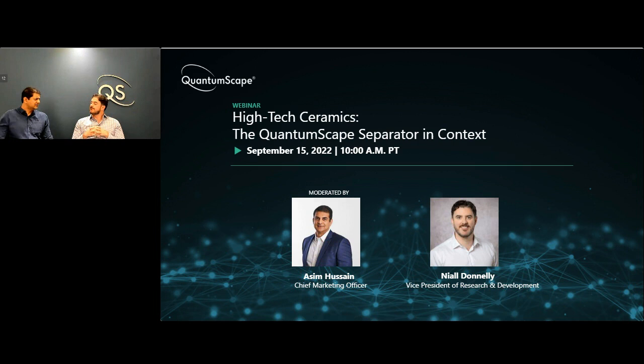Right. And is that because the separator isolates the cathode and the anode so distinctly as a solid state? That's right. In a conventional lithium ion, you have to be very careful about the compatibility of your electrolyte with both the high voltage on the cathode side and the low voltage carbon on the anode side. In our separator, we know that we're already compatible with lithium metal on one side. And so long as we're compatible with the catholyte or the host medium for the lithium ions on the cathode side, then we can really adapt to any particular cathode configuration that we want.